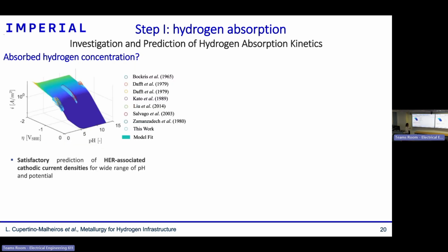Finally, I tried, with the data acquired and that approach I mentioned in the beginning, the reaction rate approach, to get how much hydrogen gets absorbed. By fitting my data and data from the literature, we can satisfactorily predict the current density associated with hydrogen production, potential, and pH.